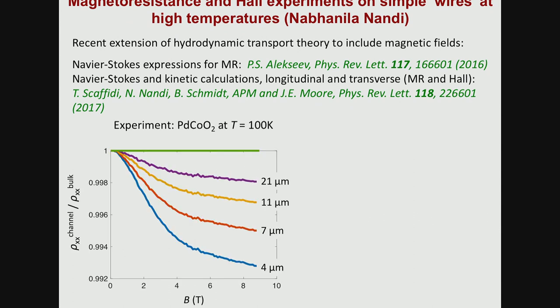So we then went away and did some experiments to test what he'd been coming up with. These are deliberately chosen to be quite high temperature experiments to try to get our supposed electron-phonon length down nice and short. That means, though, that all the internal length scales are very small compared to the width of our devices. So it means that the experimental signal is small. But everything looked very exciting.